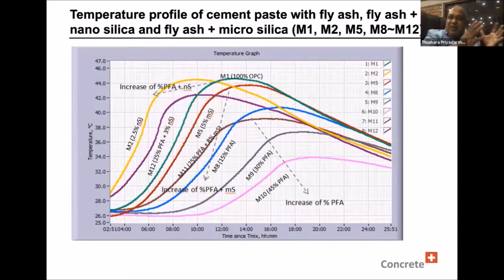As we were discussing about high performance fly ash, microsilica and all others, this is how you can bring your temperature curve down with pozzolanic material. As an example, the green line is 100% OPC. If you use it, your temperature will be like this. This is just a trial which was done for mortar. When you add fly ash into it, it drastically goes down. So say with 30% fly ash, the temperature will go down drastically. Because if you want strength again, you have to add microsilica. If you add microsilica, this moves the other way around as well, but still compared to OPC it is quite good.